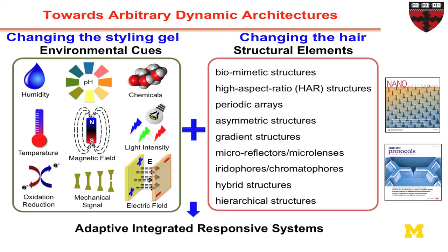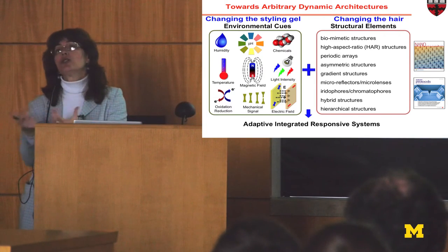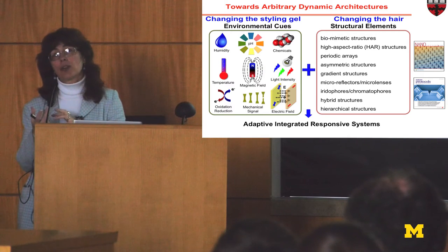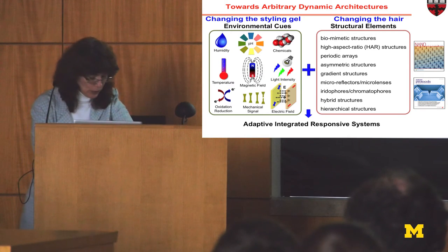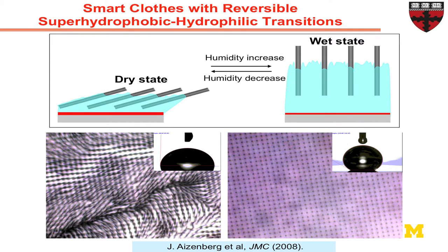So there's a range of things you can do by playing with other things, not only moisture, but playing with magnetic fields that are temperature responsive, pH responsive, light responsive, mechanical signal responsive gels, which can now be combined together with the skeletal, with bones of the structure, but also can have different symmetries. So you can induce different types of movement, different types of reconfiguration, and different types of motion in these structures. So one can do now, if we talk about hydrophobic and hydrophilic, now let's try to combine it with what I was talking about before. And what if now I take the gel that's hydrophilic and the structures that are hydrophobic?